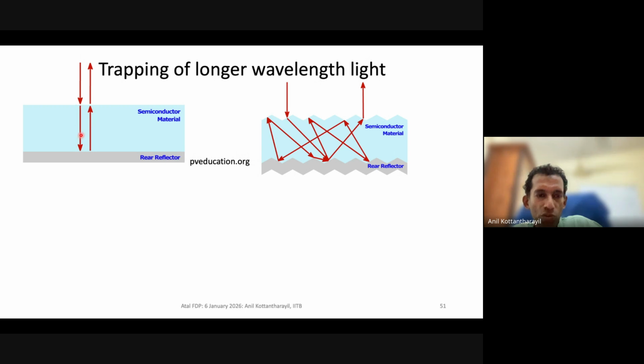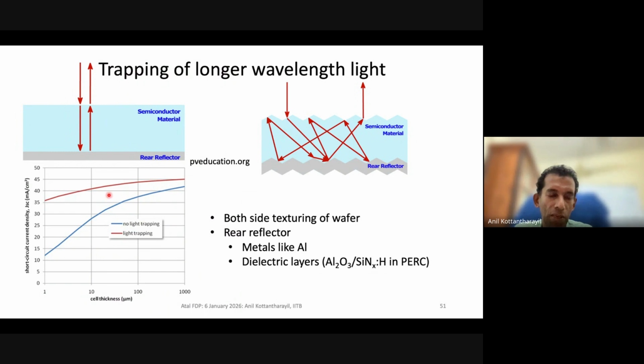So instead of one pass, let's say this is 100 micrometers. If it goes through once, you have 100 micron, right? But if you are able to bounce it around 50 times, then effectively you have increased the optical thickness of the solar cells to 5,000 microns, right? 50 into 100, so 5,000 microns. So with that, you can actually get very good current and efficiency. You can see that with no light trapping, the short circuit current density can be very small, but if you create structures to trap the light inside the semiconductor, you can get very high currents and hence efficiency.